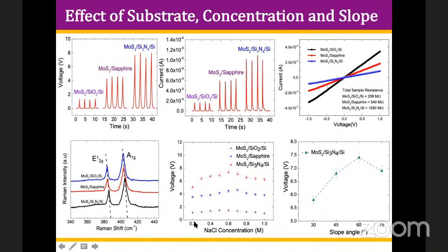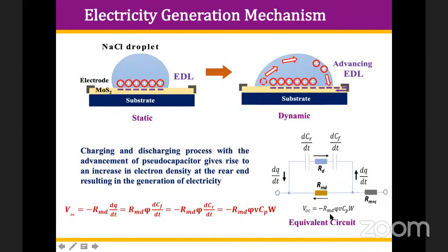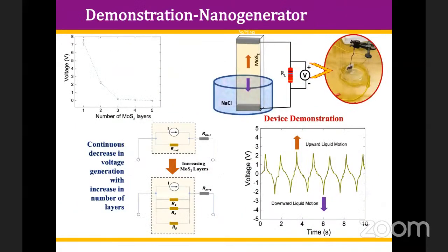And these are the NaCl. We changed the NaCl concentration, and you can see the response is almost flat, and maximum response is obtained with silicon nitride substrate. We tried to change the slope angle, to see at which angle the energy generation or voltage is more. We found at 60-degree angle, the generation of voltage is much higher as compared to the other slope angles. So this is a mechanism. I am skipping this mechanism part.